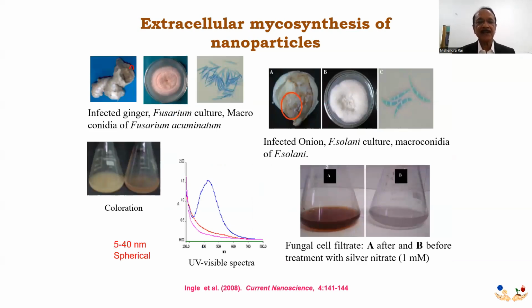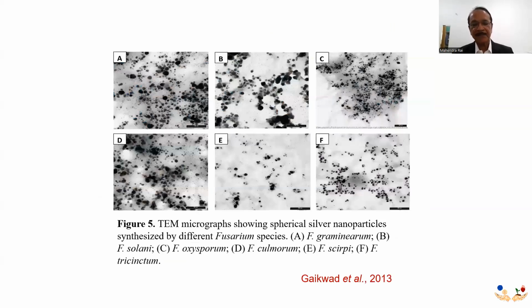Here is an example which I would like to demonstrate. Fusarium acuminatum and Fusarium solani were isolated from ginger and onion, respectively. We synthesized silver nanoparticles of 5 to 40 nanometers. We prepared the extract of these fungi and treated it with 1 millimolar silver nitrate. And the nanoparticles are very, very bioactive against different pathogenic fungi. Among the Fusarium species we have evaluated, we found several nanoparticles of silver.